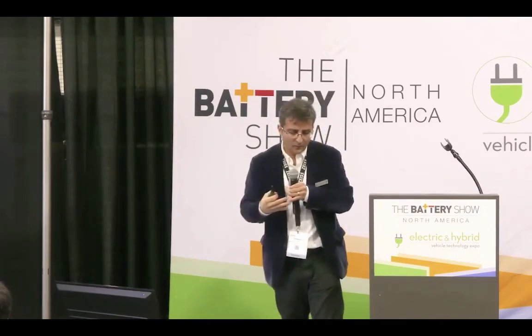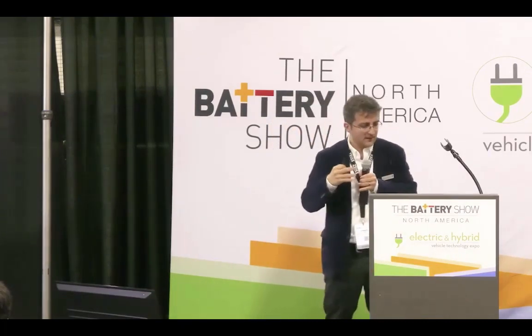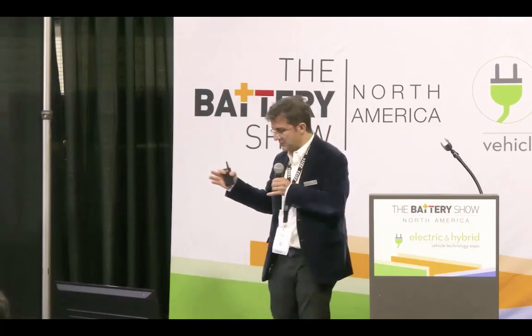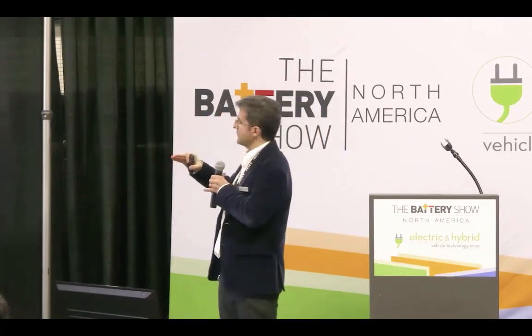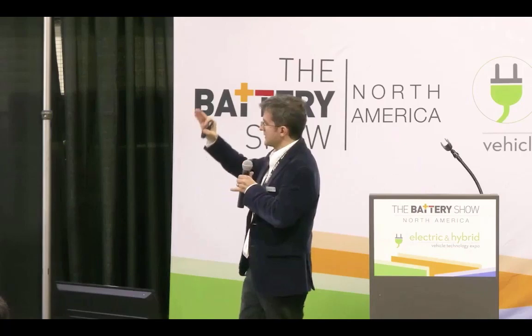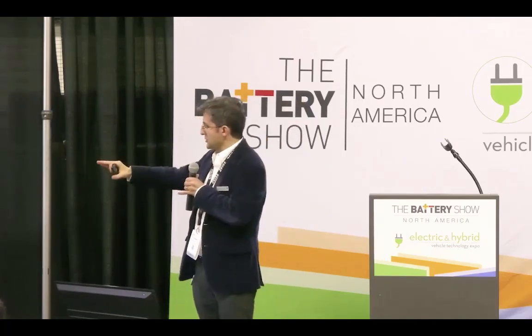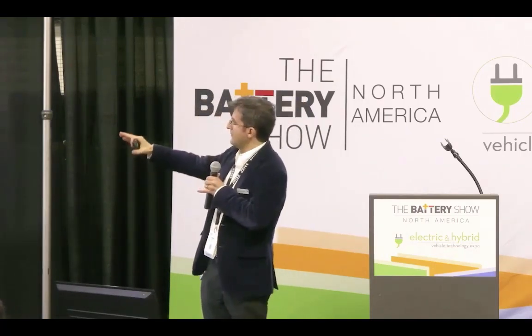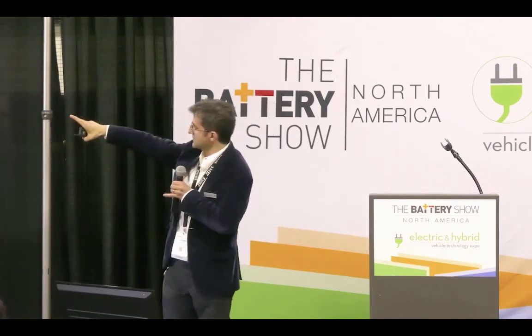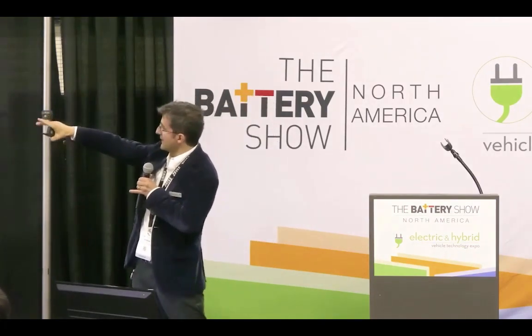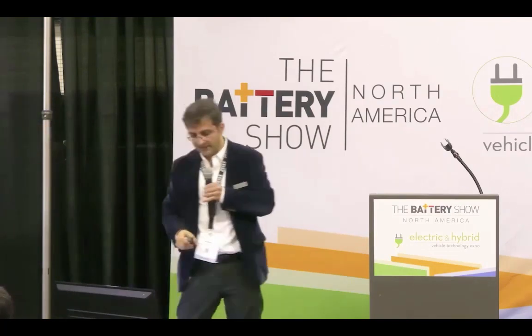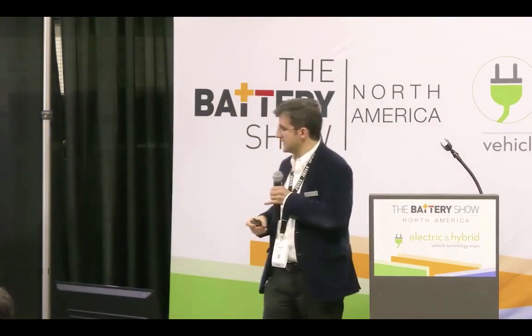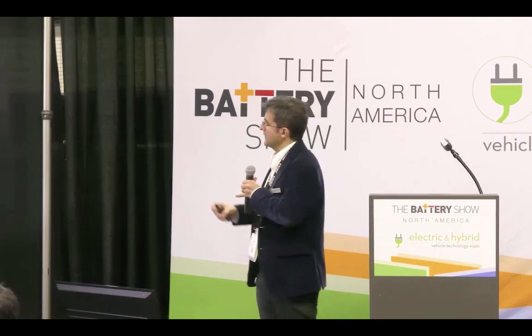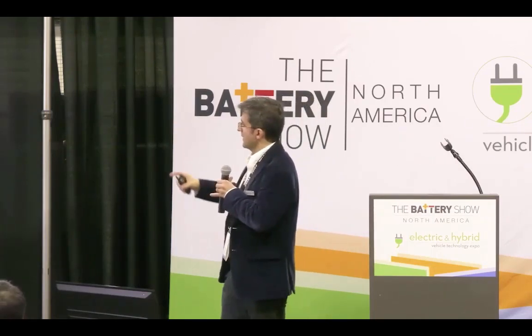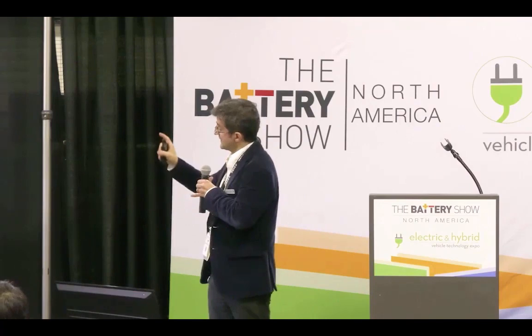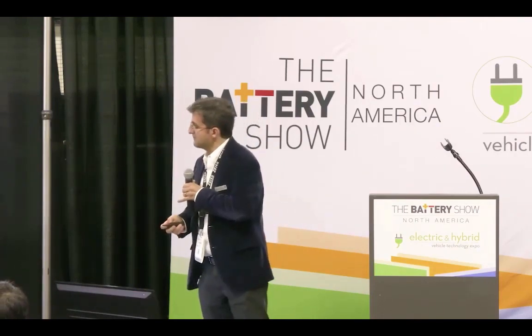So we saw aging, looking at what happened with some of the particles, but it is also very useful to see how the electrodes are bending. And you see here, after 80 cycles, a battery cell where several electrodes at the top are bending, and they are even touching together. And this is very critical for battery manufacturers to assess. So you can do some tomographic studies of the battery.